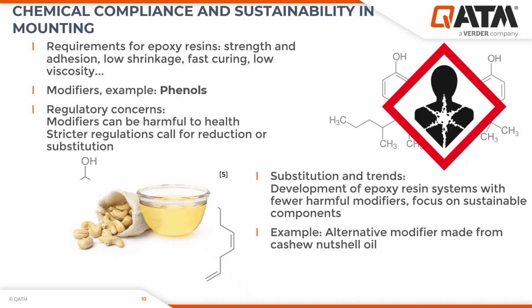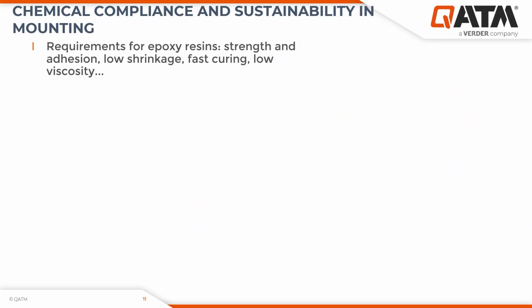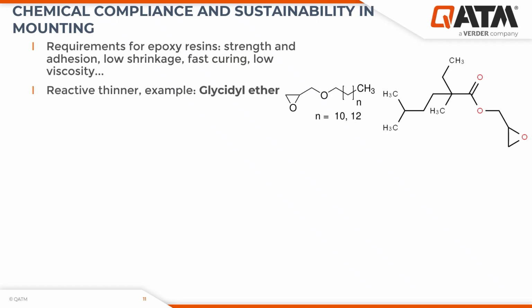We can stay for an additional example here at the epoxy resins. Another way to influence the properties of an epoxy resin, for example, decreasing the viscosity, is by usage of reactive thinners, for example, glycidyl ether. I have shown here again two different examples of glycidyl ether that are incorporated into the epoxy resin in order to decrease the viscosity. As mentioned, bisphenol A epoxy resin tends to have extremely high viscosities that make them non-applicable for materialographic purposes. And these glycidyl ethers can influence the viscosity by reducing it in comparison to modifiers like solvents or plasticizers. These are also incorporated into the epoxy resin during curing and cannot leach out after sufficient curing.